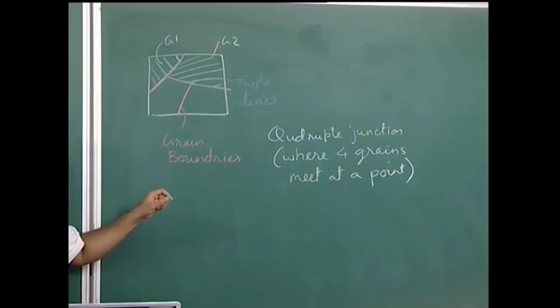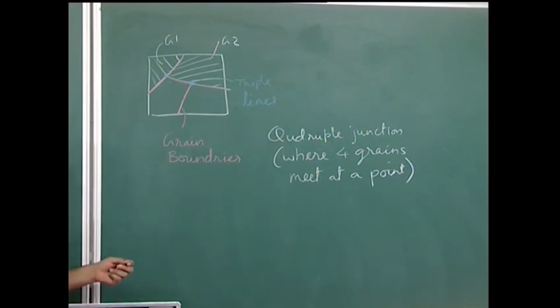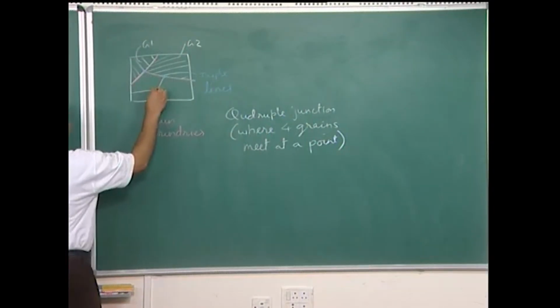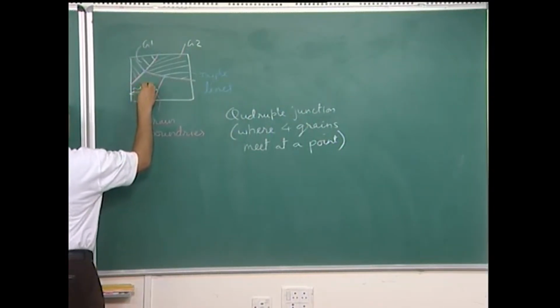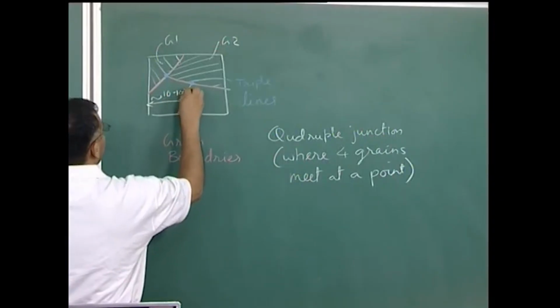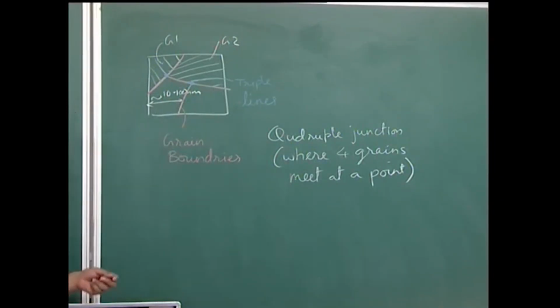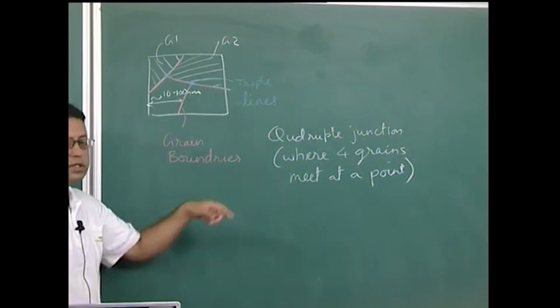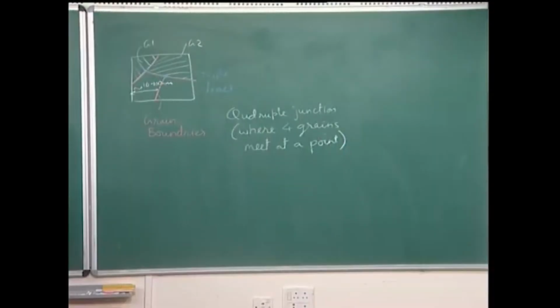But when I am talking about a bulk nanostructured material, it means that the grain size is of the order of nanometers. So, this is, for instance, maybe 10 to 100 nanometers, and therefore, in such a material, the effect of these on the density and elastic properties cannot be ignored. Obviously, needless to say, their effect on plastic properties and fracture and other behavior also cannot be ignored. Therefore, let us see how these entities affect my density.